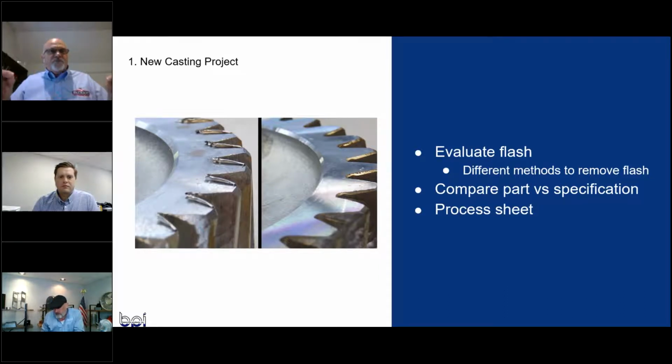Then before I do anything, after I've prepped the casting, I'm going to put it in an oven at 340 degrees for 15 minutes. I'm going to expand that casting, let that gas, we call it degassing, let all the gas, the air get out of it, cool it back to ambient. It's going to go back to its original, everything's going to be the same as it was when it came out of the box.